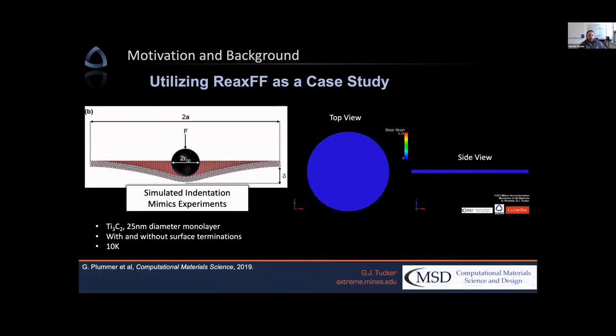So continuing that, we actually did this a few years back with Professor Gogotsi and Professor Anasori. My student, when he was a master's student at Drexel, started this, where we basically constructed these monolayer MXenes. These are bare to start, and we simulated nanoindentation of these MXenes to hopefully mimic very small scale experiments, where we couldn't reach the true length scale, but we can approximate that with this length scale. Here, what we see is a 25 nanometer diameter monolayer of Ti3C2. And like I said, we started without surface terminations, and then using ReaxFF, we were able to add in various surface terminations. And we indented these.